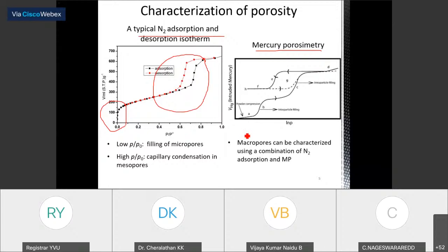In the case of macropores, this ideal assumption alone cannot give you an exact picture. So people will go for mercury porosimetry. In the case of mercury porosimetry, mercury will be pressurized into the pores, and based on this intrusion and extrusion curves, this is the intrusion curve, and this is the extrusion curve, people will characterize the macropores. So by using the combination of nitrogen adsorption isotherms and mercury porosimetry, one can characterize mesopores as well as macropores. So this is about characterization of these porous materials.